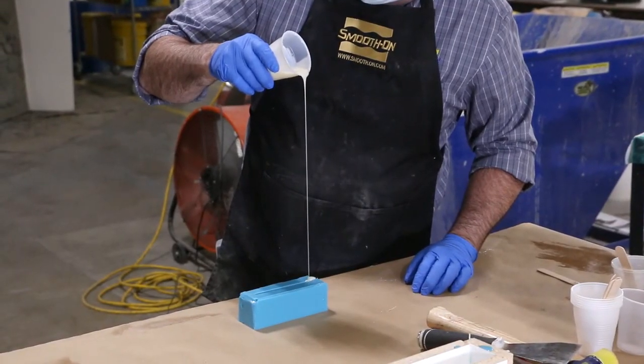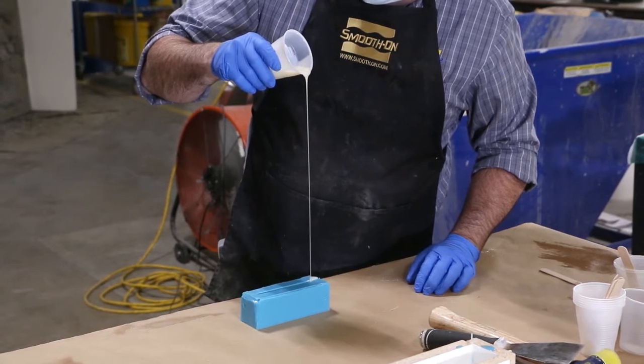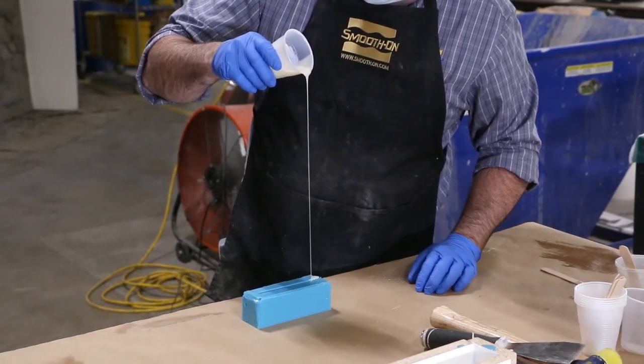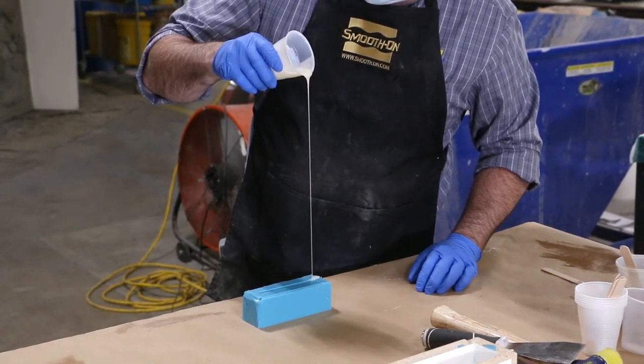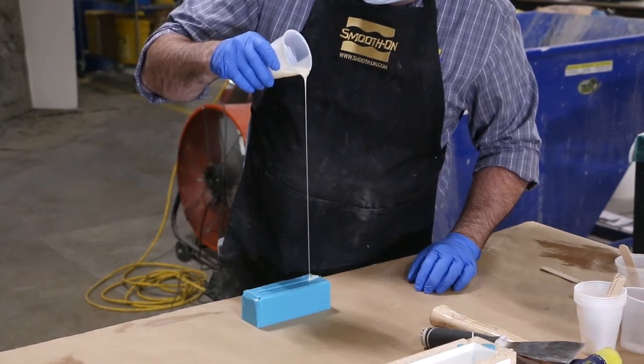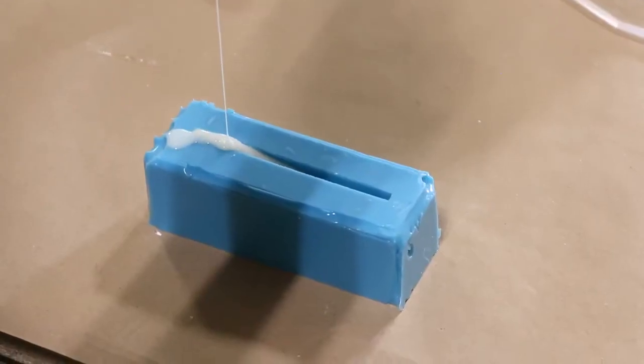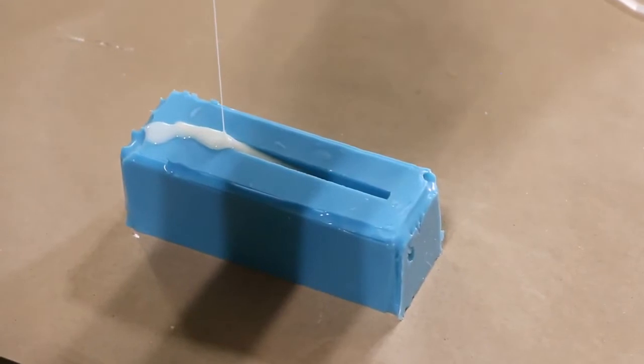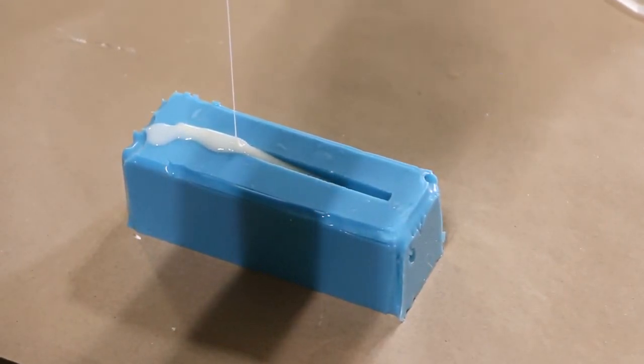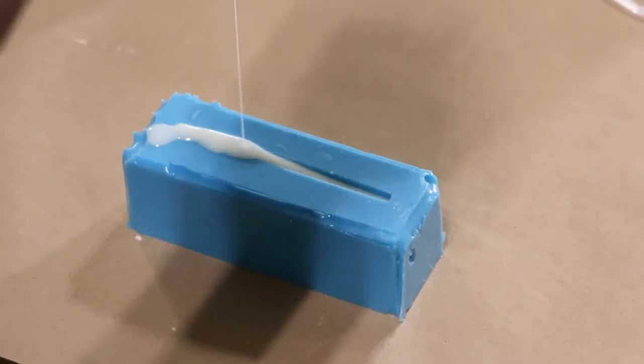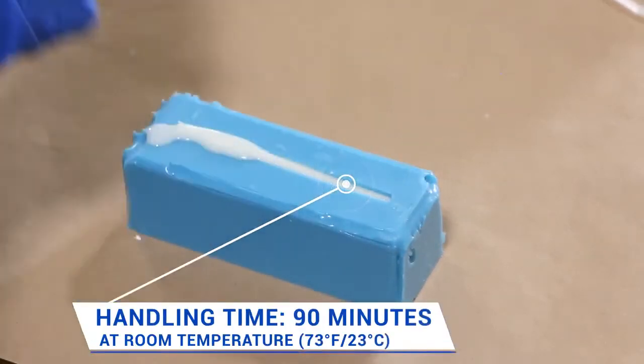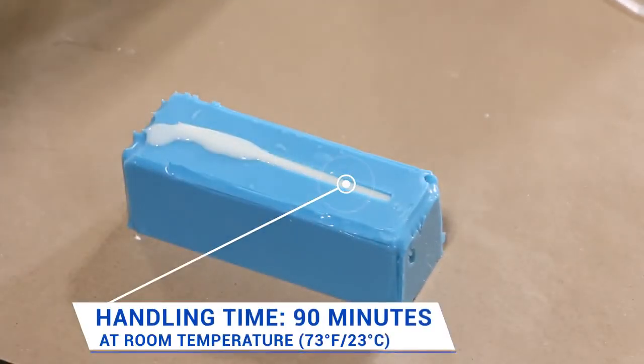Since I chose the MoldStar 16 silicone, there is no need for any release agent. This is another reason I like to pair Task 16 with MoldStar 16 when making inserts and plug features for casting concrete. They are fast, and there's no need for release agent when casting the urethane into the silicone. The material is allowed to cure for 90 minutes before demolding.